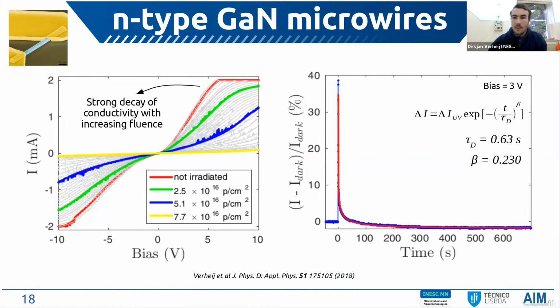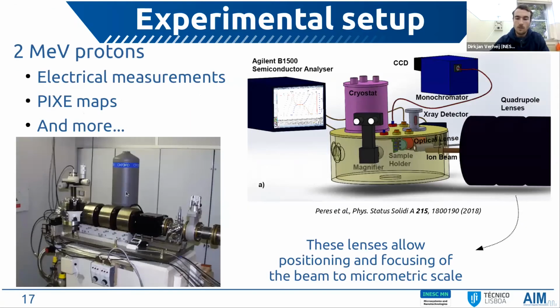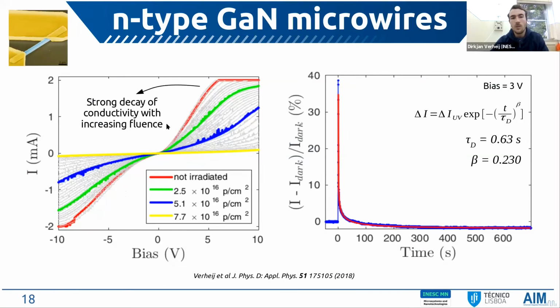I will now deviate a little bit from the way I presented my data so far. Right now, I'm only going to talk about the n-type microwires to begin with. I want you to look at this graph on the left side, which shows the strong decay of conductivity with increasing irradiation fluence. Despite the high radiation resistance of the devices, the damage created by the proton beam is still high enough to induce a strong decrease of the conductivity of the devices.